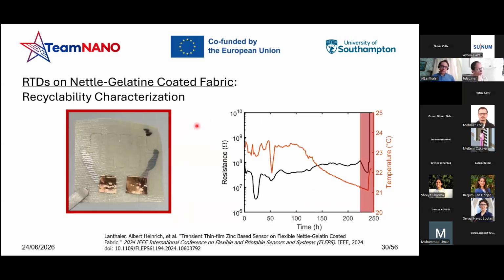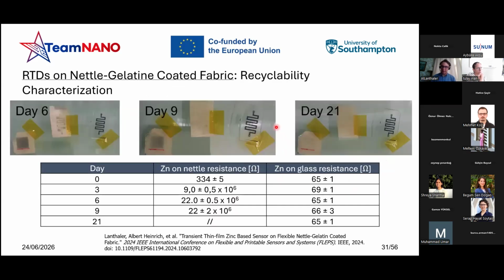To the previous issue we encountered, as you can see here, monitoring the resistance of the device over time, we were actually able to see the device fading away. So within 10 days, the device was completely transparent, and a loss of content was encountered. The main question is: is it a matter of the formation of a zinc oxide layer due to the oxidation of zinc exposed to air, or is it a matter of the absorption by gelatin of the zinc layer itself?